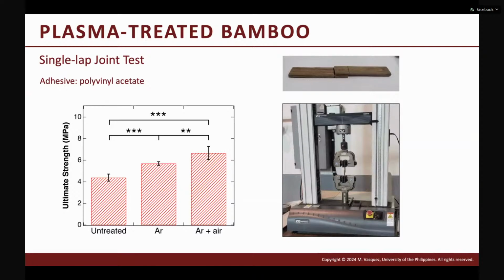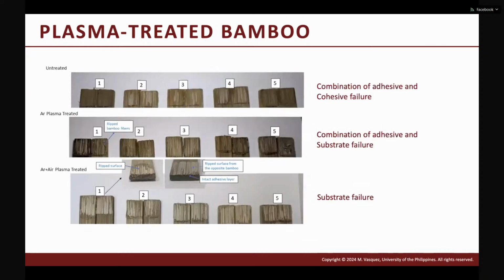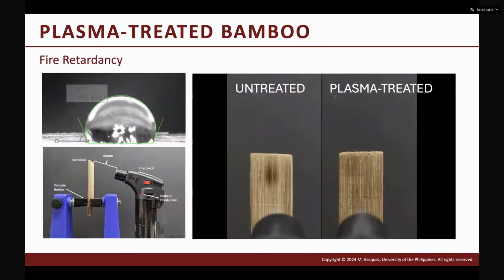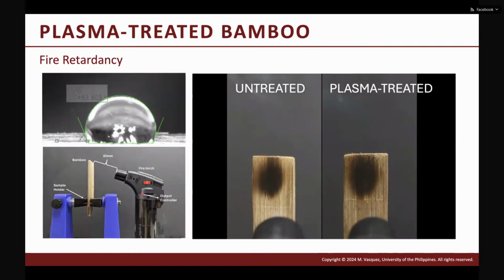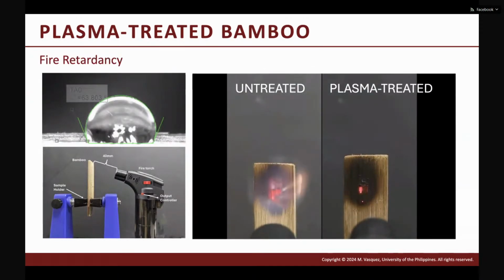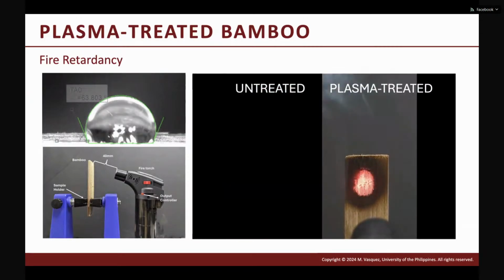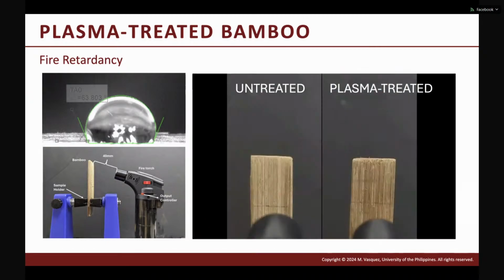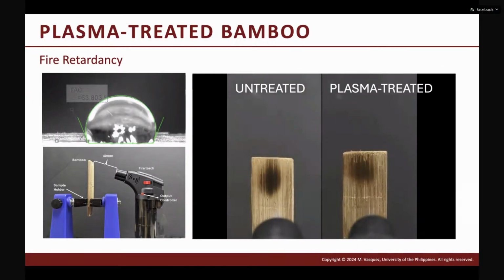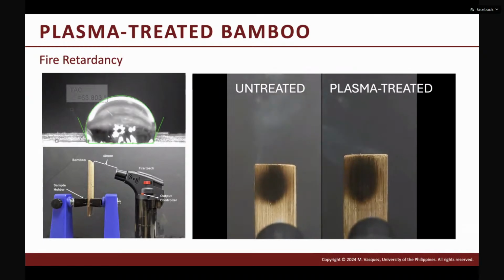Now, take note, we're using polyvinyl acetate because right now we cannot use formaldehyde-based adhesives. And this is the result. So we have increased adhesion strength for plasma treated bamboo. This one is the fire retardancy test, and we are also able to improve the fire retardancy of bamboo after plasma treatment. So as you can see here, you don't see any flame even after 90 seconds. But before, if it's untreated, you will see flames or ignition even after 30 seconds. So that's the effect of plasma treatment.